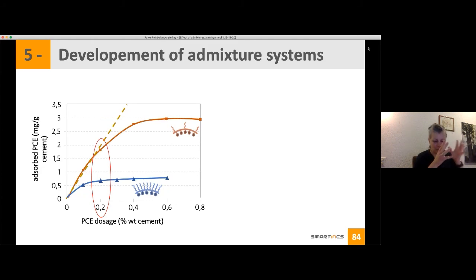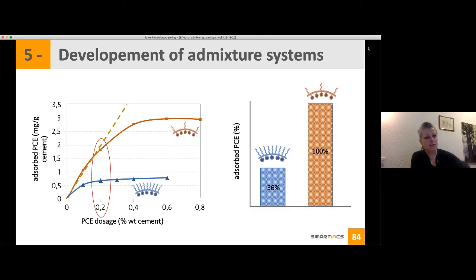So now if I look at this data a bit differently, I say, okay, I will take a dosage of 0.2 per weight on cement. And okay, what does it mean? It means that for my red PCE, I'm still on a dotted line. So everything I have put in the system is adsorbed as reactive.